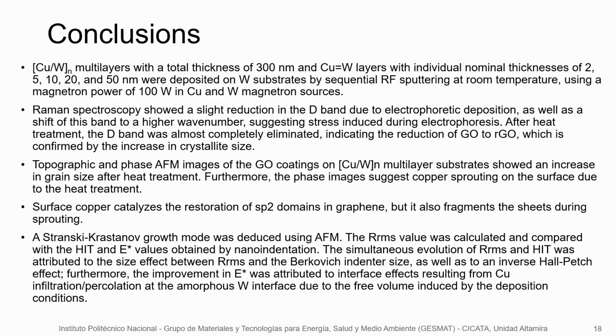As conclusions, copper and tungsten multilayers with a total thickness of 300 nanometers, with copper and tungsten layers with individual nominal thickness of 2, 5, 10, 20, and 50 nanometers, were deposited on tungsten substrate by sequential RF sputtering at room temperature using a magnetron power of 100 watts and copper and tungsten magnetron sources. Raman spectroscopy showed a slight reduction in the band due to the electrophoretic deposition, as well as a shift of the band to a higher wave number, suggesting stress induced during electrophoresis. After heat treatment, the band was almost completely eliminated, indicating the reduction of graphene oxide to reduced graphene oxide, which is confirmed by the increase in crystal size.